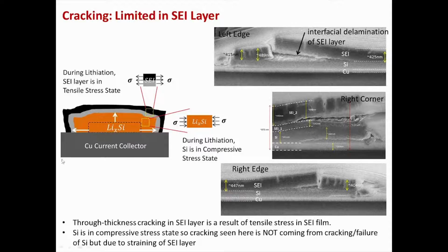To make this point clearer, after cycling we did some ex situ FIB cross sections of these cycled islands, and you can see that the cracks of the SEI are mainly focused on the edge regions or the corner regions of the island, and you can also clearly see the partial interfacial delamination of the SEI layer. It is very clear that the silicon is intact. There is no cracking, although there is partial debonding of silicon in the edge region, but it is not getting cracked. So the cracking is mainly limited to the SEI layer.